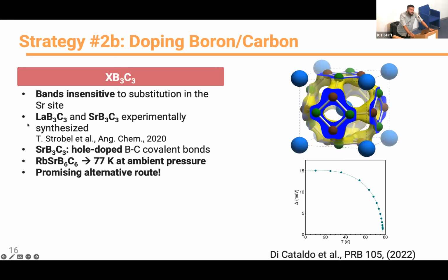But we studied the effect of substitution of a lot of possible metal ions, and the band structure turns out to be very insensitive to these substitutions. So the effect is really that the Fermi energy shifts without disturbing too much the bands. The effect is that we turn the system into a hole-doped metal. And if we predict the critical temperature, we get reasonable TCs. So we tried to play a bit with all possible substitutions, and the best we could find was a 50-50 doping of rubidium and strontium, for which we predict a critical temperature of exactly 77 Kelvin, again with density functional perturbation theory and isotropic Migdal-Eliashberg. So this is, again, a promising alternative route.